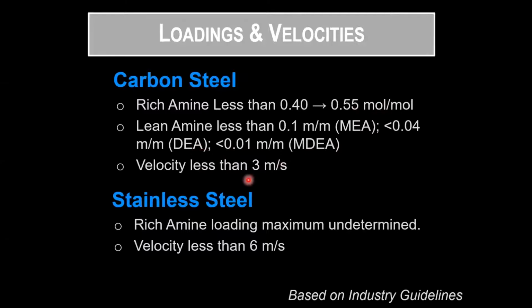And we want to make sure our velocities are controlled in our piping. Less than 3 meters per second is kind of the industry guideline. And if you put in stainless steel, we can flow higher velocities. Max rich loading is kind of undetermined. There are plants that have pushed their rich loading to 0.75 mole per mole by putting stainless steel through the entire rich side of the facility, but that's sort of a corporate decision made by